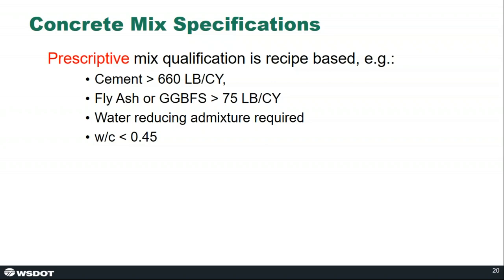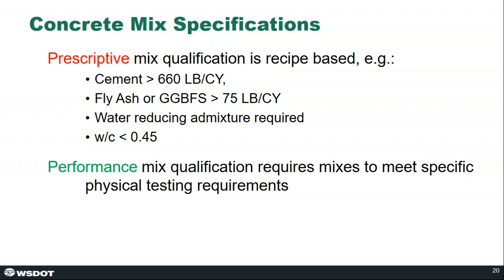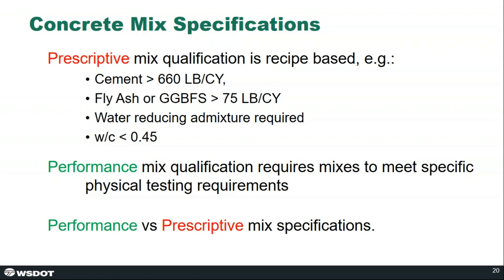And this sort of approach works for most of the concrete that we place in Washington state, but it hasn't always led to the best results, particularly with bridge decks. And our current approach now is to take a more performance-based mix qualification approach where the concrete itself has to meet specific physical testing requirements prior to being qualified for use in a bridge deck. And so we can focus on the properties we're really interested in, like freeze thaw performance, shrinkage, and chloride resistance.